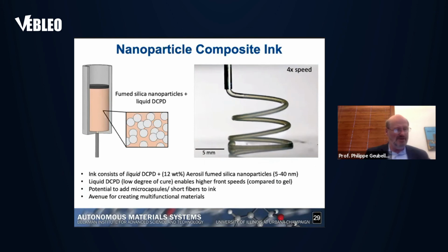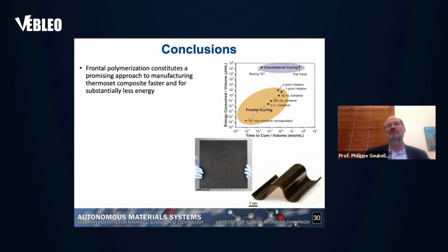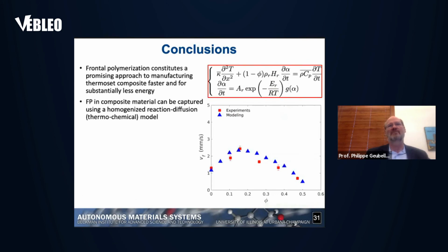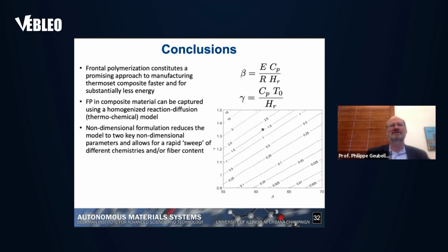So I will stop here. I will simply conclude that frontal polymerization constitutes a promising approach to manufacturing thermoset composite faster and for substantially less energy than conventional methods. We can capture this process by using the fairly classical homogenized reaction-diffusion equation or thermochemical model. Obviously, we can combine this also with a mechanical component, right?